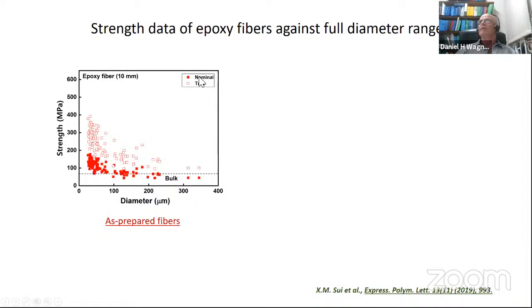And the nominal value is plotted in full symbols, and the true value, as I mentioned before, is plotted in open symbols. And you see that below a certain diameter, which is around here, 90 micron or so, you get this increase from the 67 megapascal value up to close to 200. And if you calculate the true strength, it goes even much higher.